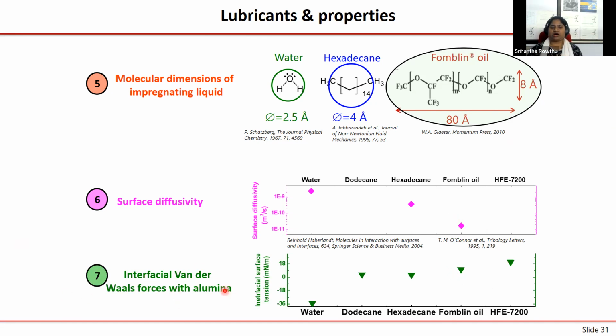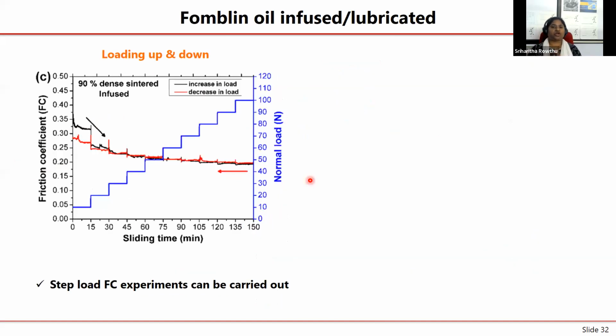So that's what we tend to characterize with so-called interfacial van der Waals forces of attraction with alumina. And most of the liquids, except water, are reasonably in the same range. Water definitely is a special case because it can form hydrogen bonding with aluminum oxide. Anyways, the rest of the properties of water are not the best. Therefore, Fomblin oil for the surface diffusivity and capillary process is not the best, but for the other properties, it has actually been very nice. So overall, we can say that among all the liquids for the tribological testing, Fomblin oil was the better or best lubricant.